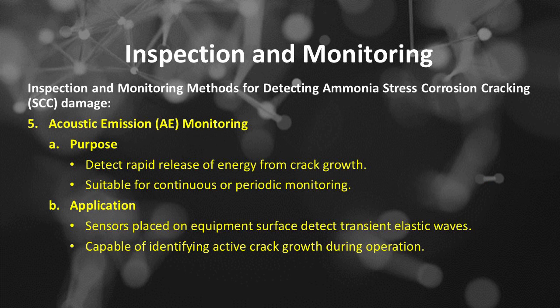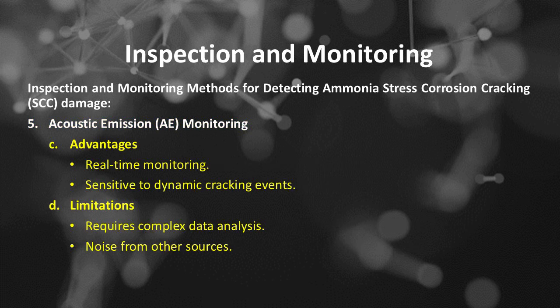Number 5 of inspection and monitoring methods for detecting ammonia stress corrosion cracking damage is acoustic emission monitoring. It is purposed to detect rapid release of energy from crack growth. It is suitable for continuous or periodic monitoring. Application of acoustic emission monitoring: sensors placed on equipment surface detect transient elastic waves, capable of identifying active crack growth during operation. The advantages are real-time monitoring and sensitivity to dynamic cracking events, and the limitations are that it requires complex data analysis and noise from other sources.